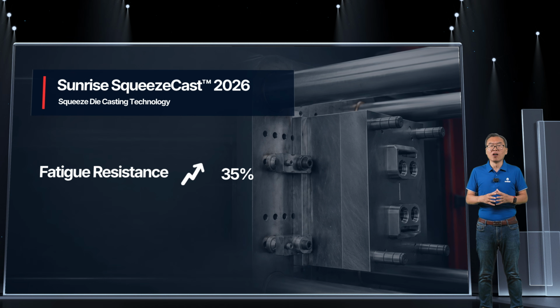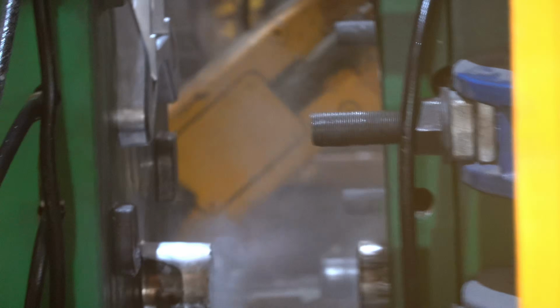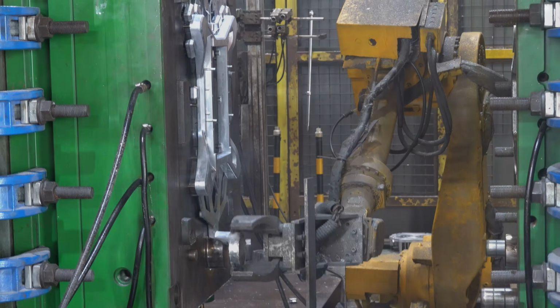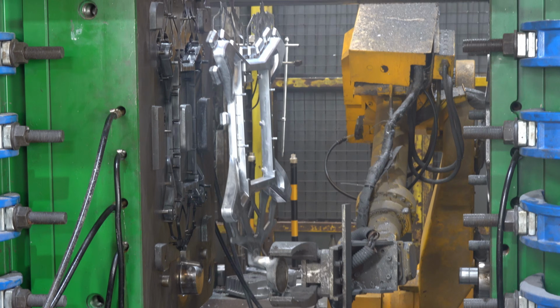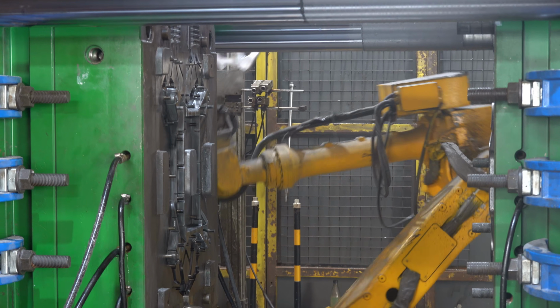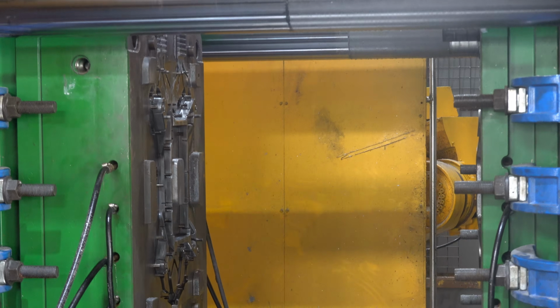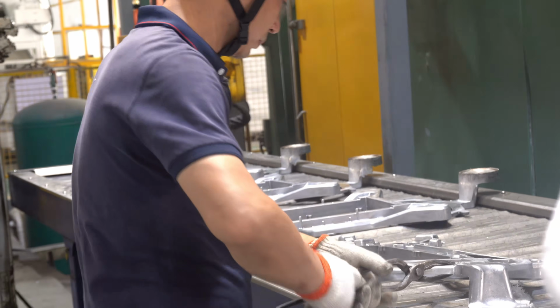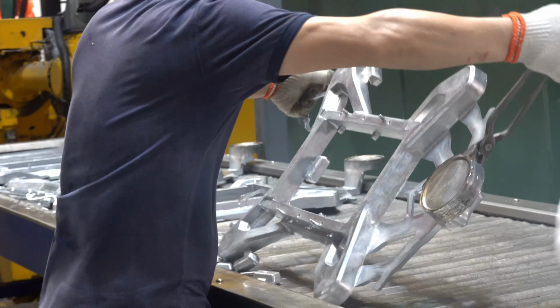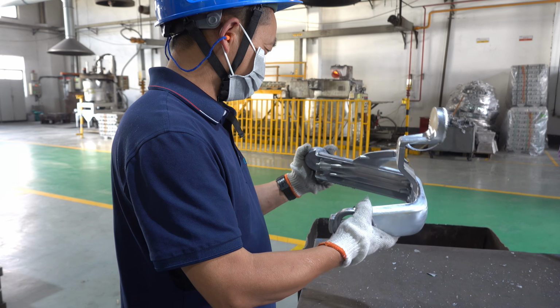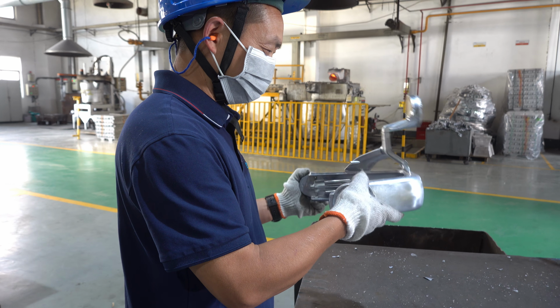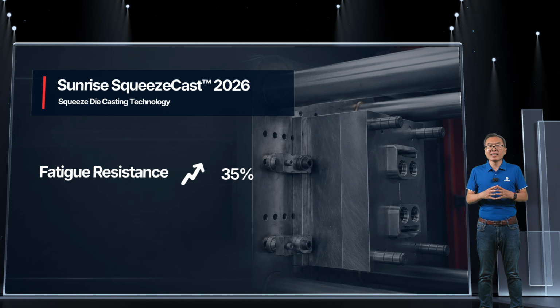Finally, we improve long-term strength with Sunrise Squeeze Cast 2026 squeeze die casting technology. Squeeze casting is not simply adding pressure, it is controlling when to press, how much pressure to apply, how long to hold it, and whether displacement is stable. This helps reduce shrinkage and looseness in thick areas, making load-bearing zones more compact. In target applications, squeeze casting can improve fatigue resistance by 35%.